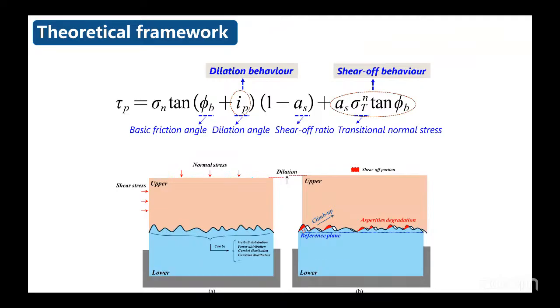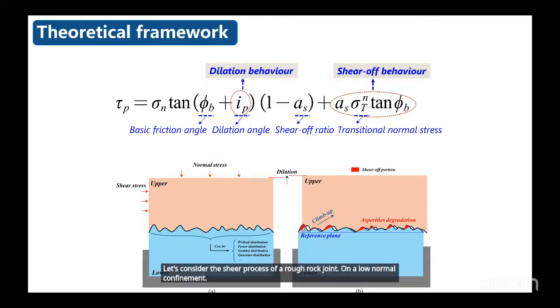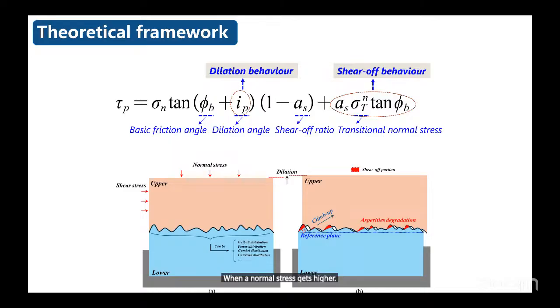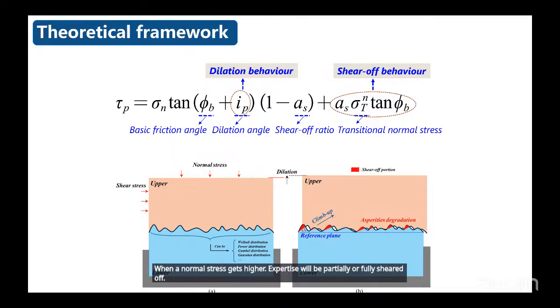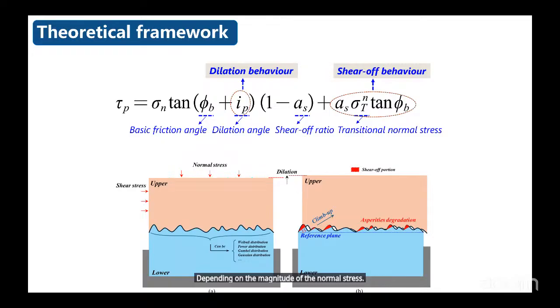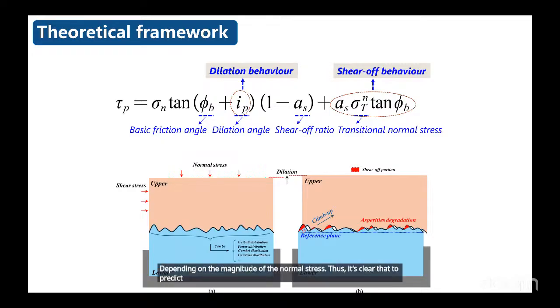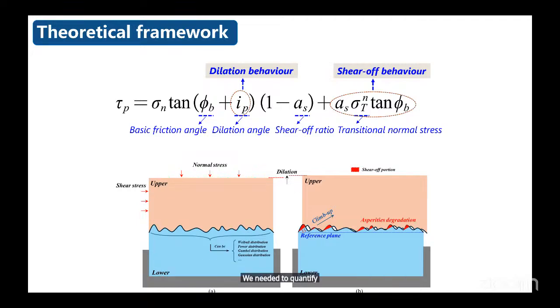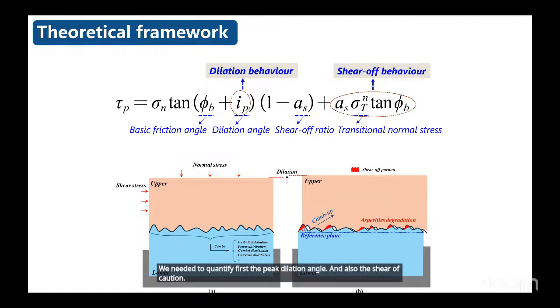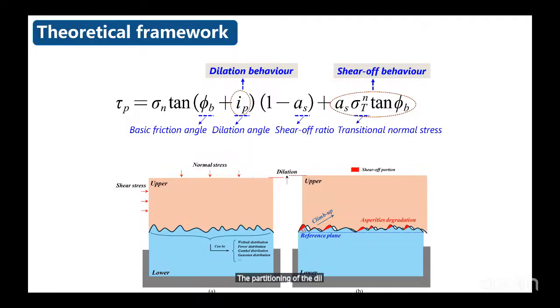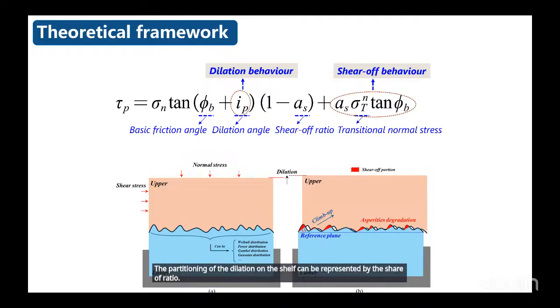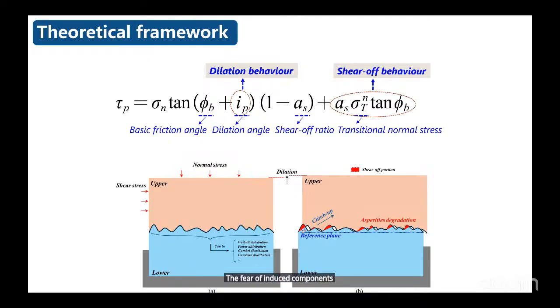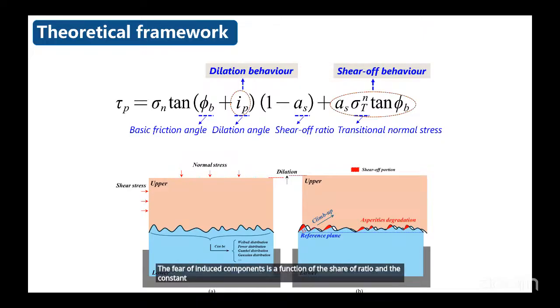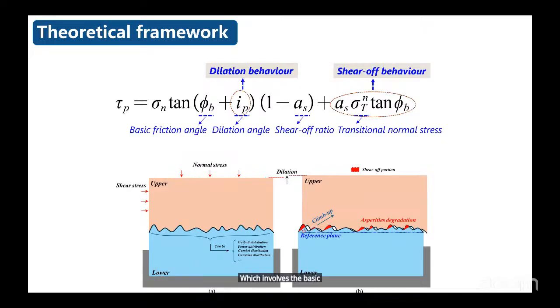Let's consider the shear process of a rough rock joint. Under a low normal confinement, the asperities will climb over each other and yield dilation. When the normal stress gets higher, the asperities will be partially or fully sheared off, depending on the magnitude of the normal stress. Thus, it's clear that to predict the shear resistance, we need to first quantify the peak dilation angle and also the shear-off portion. The partitioning of the dilation and the shear-off can be represented by the shear-off ratio. The shear-off induced component is a function of the shear-off ratio and the constant asperity strength, which involves the basic friction angle and the transitional normal stress.